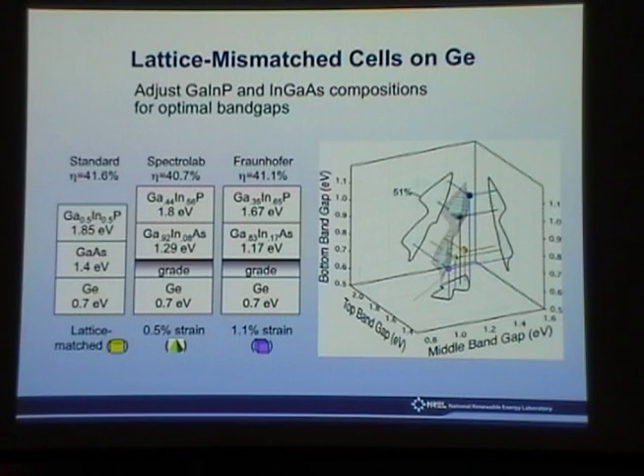So there's been progress made on these germanium-based cells. This is the standard one. And here are two manifestations of a lattice mismatch, both on germanium, but now we put in a grade and changed the top two subcell band gaps. Instead of 1.4 and 1.85, we've lowered them a little bit here and considerably more here. And these two cells represent the green and the pink-purplish dots on this graph. They're getting closer to the optimum of that bottom lobe. You don't really see any increase in efficiency, but you don't see a decrease either, and that's important. It means that, at least at this level of research, we've achieved comparable efficiency with a more optimal band gap, and it creates a platform for further improvements. And if these efficiencies were down in the 30s, I would say that the lattice mismatch is not working well. But what you can see from these results is that it is working well.